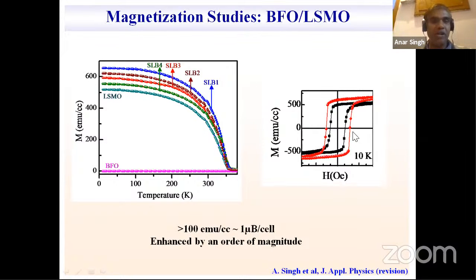And we have also investigated the magnetic properties of these heterostructures, and we find that the ferromagnetic component of the heterostructure is significantly larger than the ferromagnetic component of the ferromagnetic layer, LSMO. So this shows that in the heterostructure, the magnetic property is enhanced significantly, and this enhanced component is coming from the bismuth ferrite layer, because LSMO is already ferromagnetic.